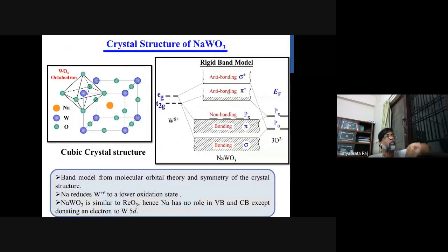So let's see what its band structure says. You have a cubic crystal structure in WO3. Because WO3 is a band insulator, the valence band is fully occupied, whereas the conduction band is fully unoccupied. As soon as you put sodium, it reduces the tungsten W6+ to a lower oxidation state, and it gives back its sodium 3s electron to tungsten 5d, and for any amount of sodium doping that electron will go to the tungsten 5d conduction band, and the system should behave like a metal.